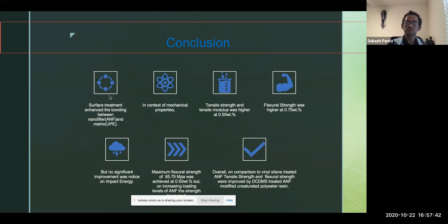So as a conclusion, surface treatment did enhance the bonding between nanofillers and matrix. In context of mechanical properties, tensile strength and tensile modulus were higher at 0.50 weight percentage. Flexure strength was higher at 0.75 weight percentage, but no significant improvement was noticed on impact energy. Maximum flexure strength of 85.75 megapascal was achieved at 0.50 weight percentage, but on increasing loading levels of aluminum nanofiber, the strength decreased. Overall, in comparison to vinyl silane treated aluminum nanofiber, tensile strength and flexure strength were improved by dichlorodimethyl silane treated aluminum nanofiber modified polyester resin.